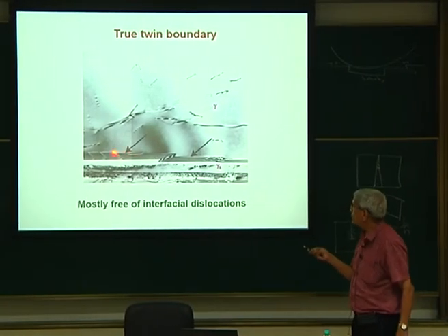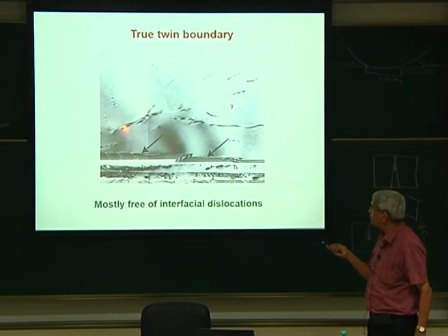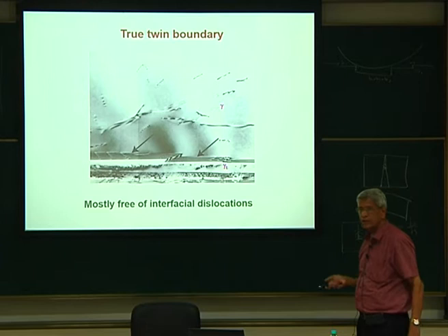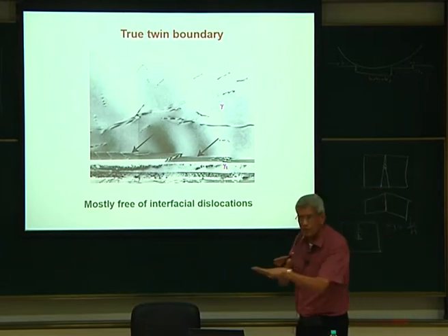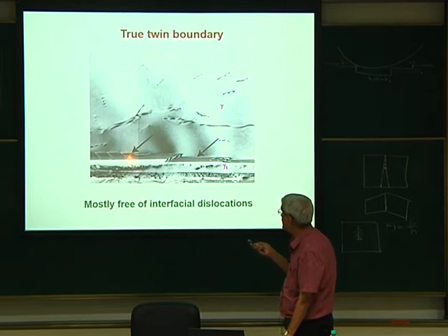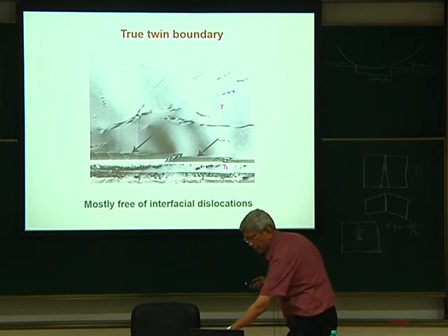This is a twin boundary, and here what has happened is that the sample is being deformed. You can see that some dislocations have entered into this boundary. We have done a detailed analysis, I am not going into it, but you can see that the dislocation brings about a small shift in that image, and essentially this dislocation can move on this boundary plane also. Depending upon the stresses which they create, they can create dislocations on the other side, and that is how deformation propagates across the boundary.